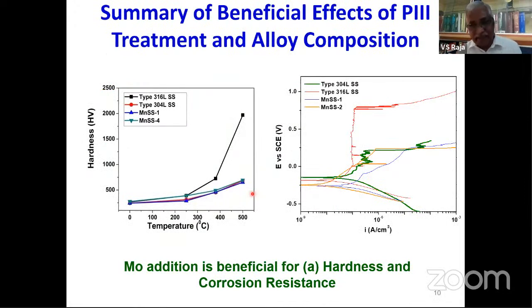You use this technique. Again, we don't have much time. You can implant nitrogen into the material, like carburizing, for example. You can have nitriding processes. You can increase the hardness very significantly, from about 250 to about 2000 hardness. You see, this hardness can be significantly improved by putting nitrogen in it. But there are some issues that we, as engineers, should be aware of.